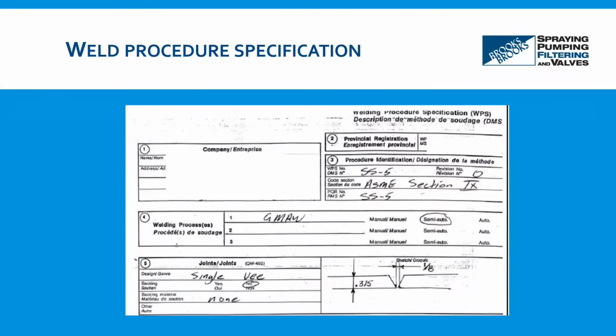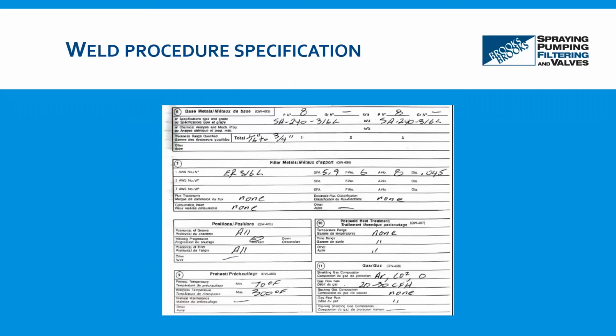Now here's a zoom in of the weld procedure specification from earlier. There are pertinent details here, such as the code reference, specifically again Section 9, and the welding process. In this case, you see GMAW, which is the fusion welding process known as gas metal arc welding, or the slang term MIG welding, the type of joint welded, and then the thickness of the coupon. Below that, we have quite a bit more detail, such as the specific material, the thickness range, the orientation of the weld, the preheat temperature, the interpass temperature, and the gas used. These are all important parameters that need to be taken into account. And again, you have to follow code. These values aren't being pulled from thin air. They are in reference to the ASME code.